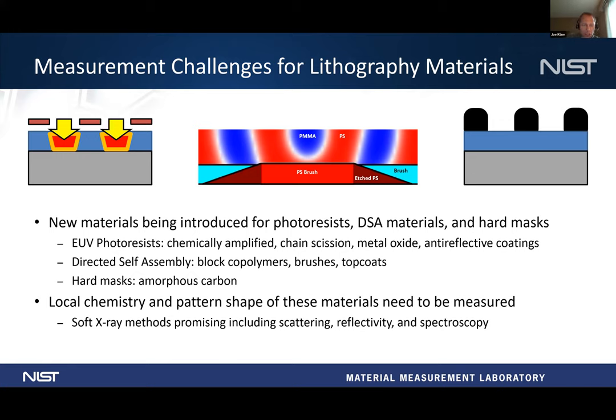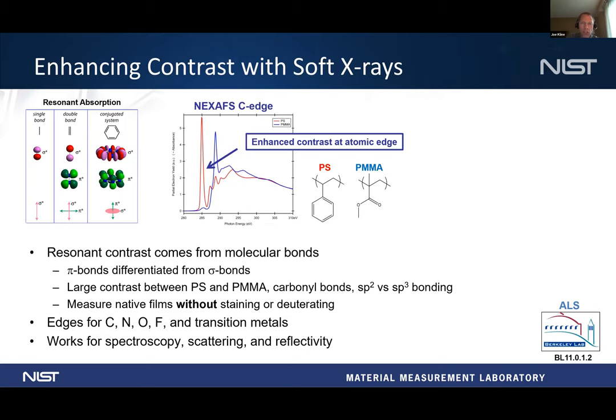And so for this, as I'll talk about on the next slide, we're using soft X-ray methods, and we're doing both scattering and reflectivity and spectroscopy, so that you can get both local chemistry and pattern shape. And so for soft X-rays, the initial part here is just showing NEXAFS spectroscopy, where you look at the near edge and you see this fine structure that's on there. And so this fine structure actually comes from the specific molecular bonds that you have in the materials. In particular here, in the middle, you can see this is polystyrene and PMMA.